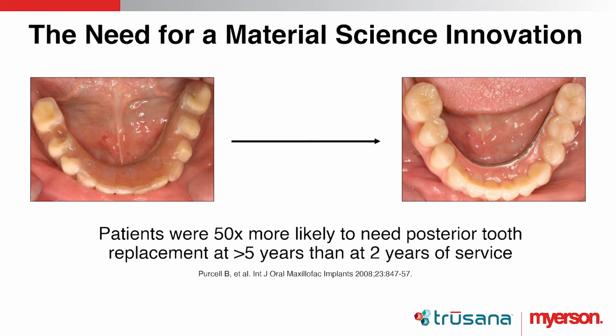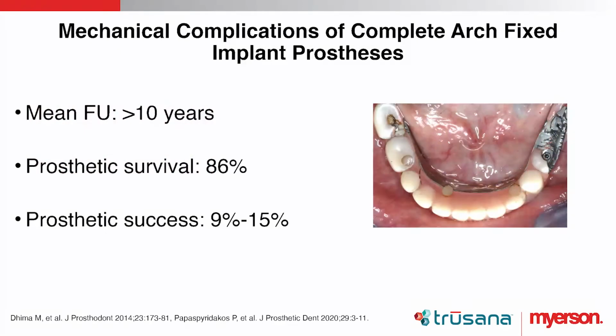So I went on to look at the literature a little bit more, and it was even more, I would say, concerning. And that is that even the definitive prostheses were having a really high complication rate. We used to brag about the fact that these had really high survival rates, and they do. Prosthetic survival is high, but the success is really low. For instance, only about 9 to 15% of these would be able to stay in the mouth without some complication over 10 years. And these were 2 systematic reviews that supported that. So this is quite an indictment on this procedure. And it's really a material issue.